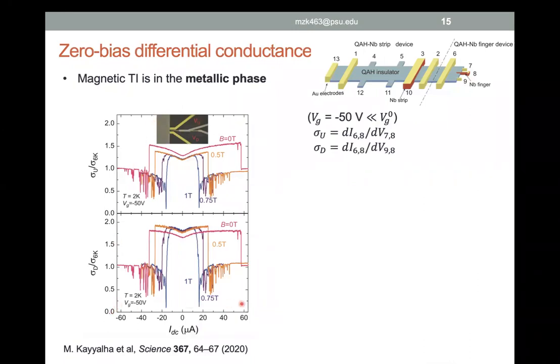And I'm sweeping the current that I'm injecting through this finger to the magnetic TI. What I see here is that below a certain value of the current, there is a jump in the conductance. So I associate this jump to the observation of some sort of Andreev reflection. The reason this is very sharp is because, again, these are not tunneling measurements. So the niobium finger transitions from superconducting to normal state, and that's why these jumps are very sharp.